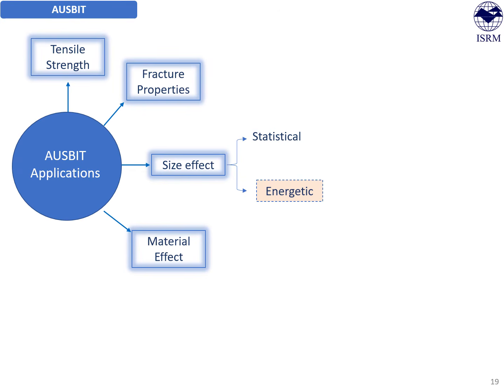In addition to this, we can also capture the effect of material change on the post-peak behavior. As we have seen in the previous slide, as the material becomes harder and more brittle, we observed a higher magnitude of snapback, whereas if the material becomes less brittle like concrete, we observe even class 1 behavior. So both class 1 and class 2 behavior can be captured by AUSBIT experimentation, which could be the result of variation in material effect.